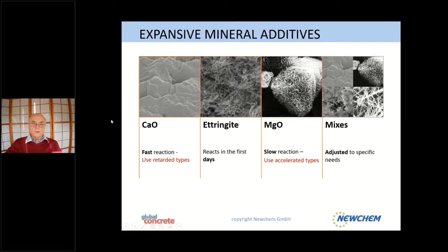Now here we have some pictures. Here we have the calcium oxide, and here we have the portlandite, the calcium hydroxide formed. This is a reaction which is quite fast. And the problem with this reaction normally is that it happens mostly in the phase when your concrete is liquid. Therefore, you lose your expanding power.